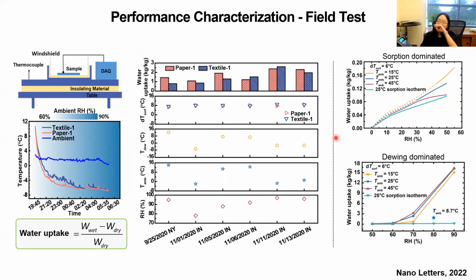So we characterized the performance. This is some field test data, and this is lab test data. As you can see here, in the low relative humidity region, sorption is the dominating mechanism, while in the high relative humidity region, dewing is the dominant one. When we were looking at these results, we realized that when dewing is dominant, the performance is not bad. But when we look at the sorption-dominant regime, especially for dry regions, the performance needs further improvement.